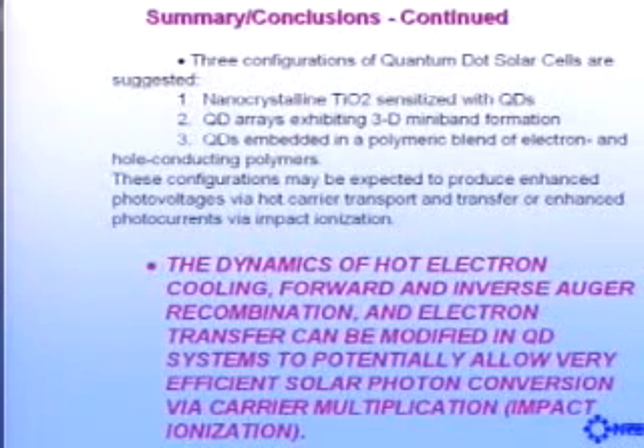And so ultimately, we believe, I didn't talk about the electron transfer because you'd also have to get the proper electron transfer dynamics, but you can control that with the spacer between the dot and the semiconductor. But we believe that based on these results, we're optimistic that we can improve the efficiency of solar photon conversion using quantum dots. Thank you.